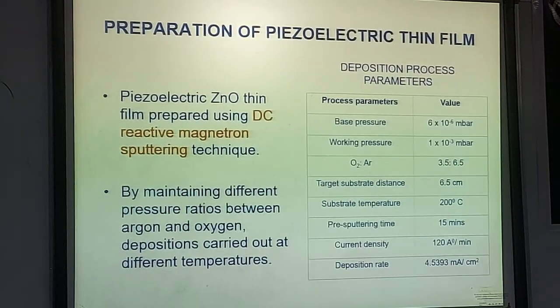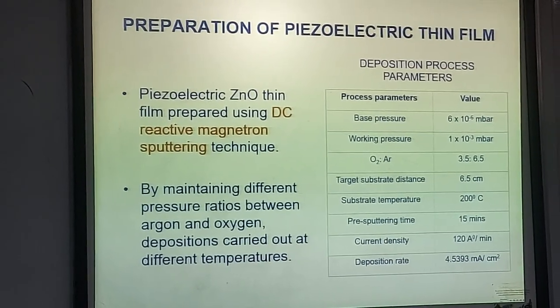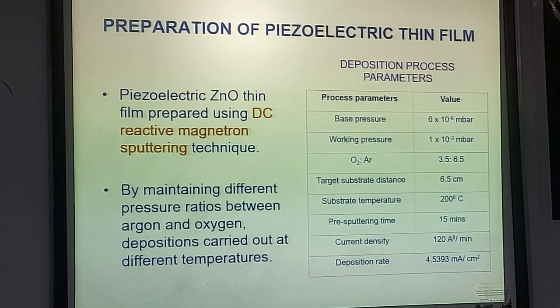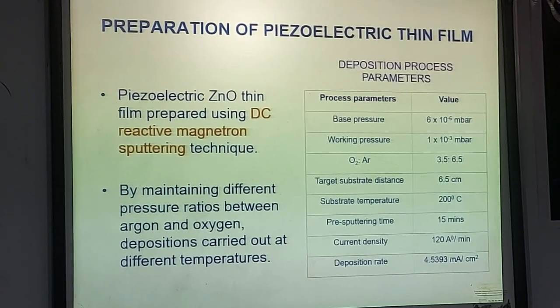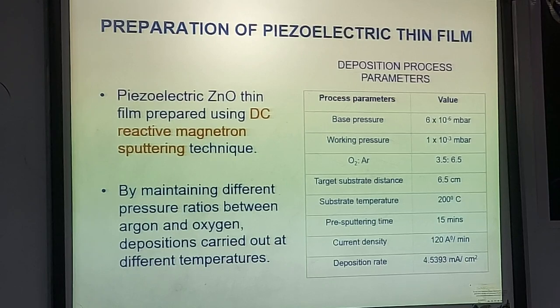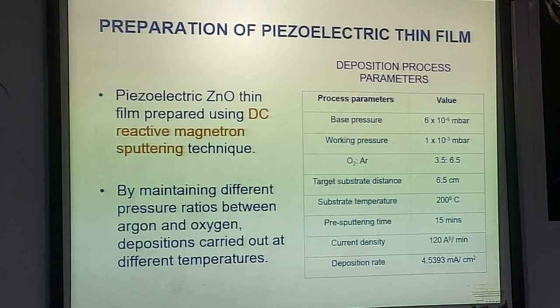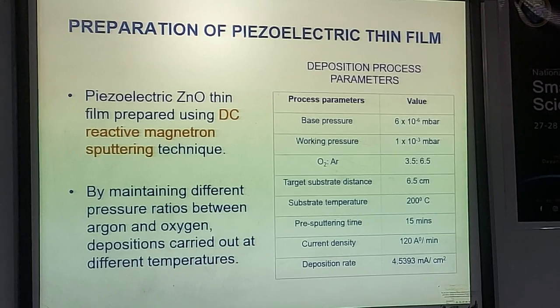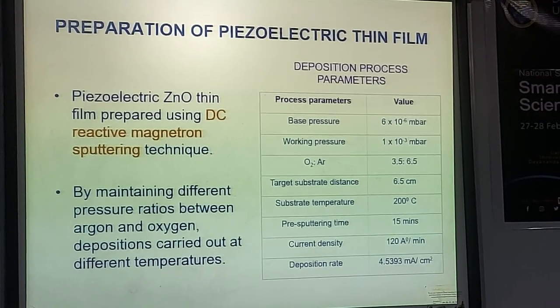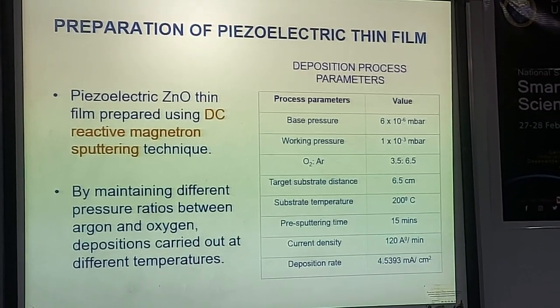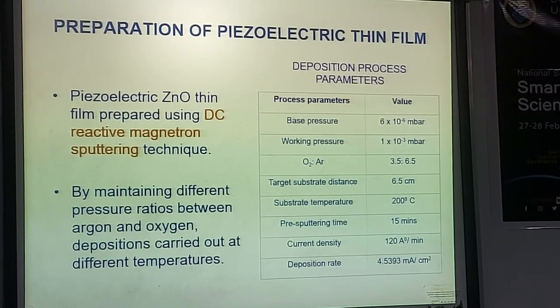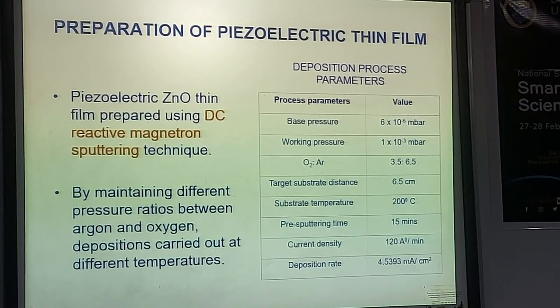Okay, so there are a number of parameters in the sputtering process which need to be optimized. The technique that we used is called DC reactive magnetron sputtering. Sputtering was done in the presence of oxygen and argon gas. These are various parameters in sputtering like base pressure, working pressure, the ratio of argon and oxygen, target substrate separation, substrate temperature, many things. So in order to get a good piezoelectric zinc oxide, all these parameters need to be optimized. This optimization was done by my student. These are the optimized parameters.